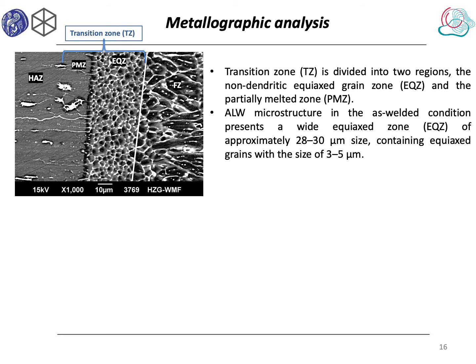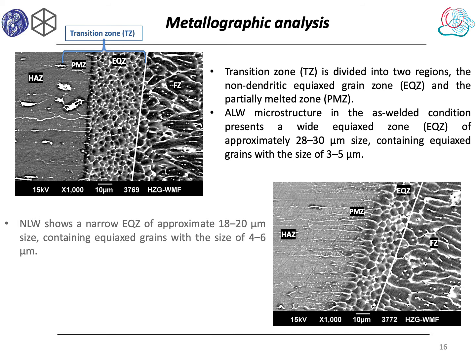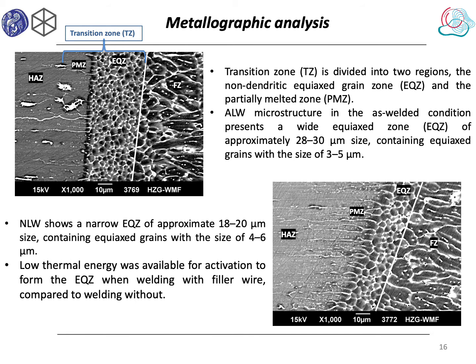For the metallography analysis of autogenous welds and non-autogenous welds, the transition zone is divided in two more zones: the equiaxed zone and the partially melted zone. The equiaxed zone contains equiaxed grains with random crystal orientation. The fusion zone next to the equiaxed zone is composed of columnar grains and in the center of the fusion zone of equiaxed dendrite grains. Non-autogenous welds show a narrow equiaxed zone due to the low thermal energy during welding when compared to the autogenous welds.